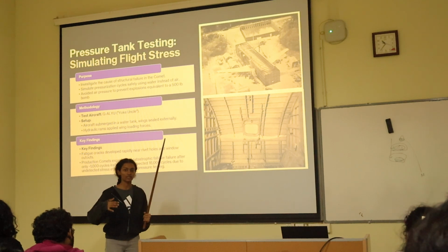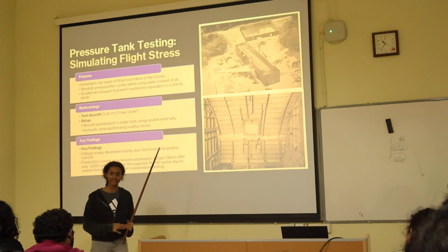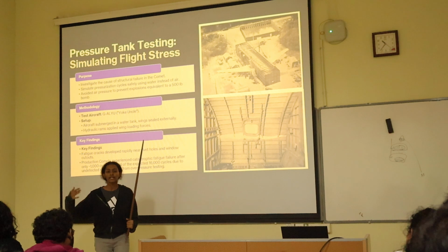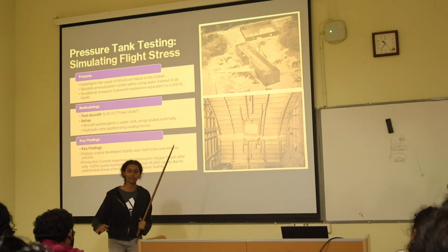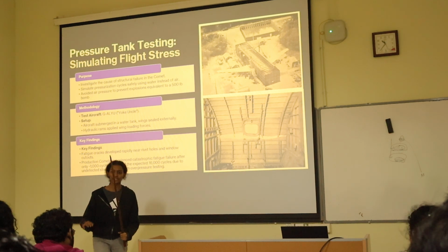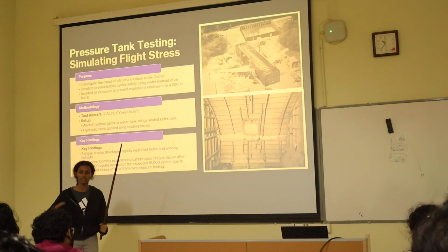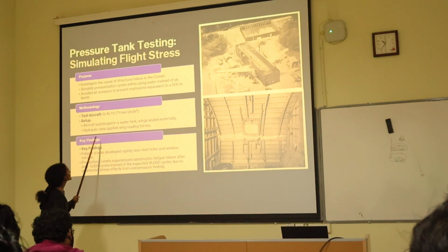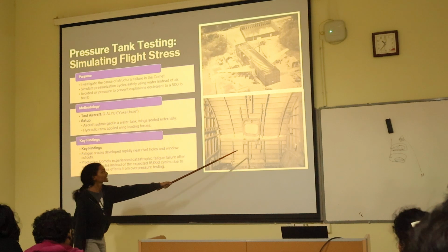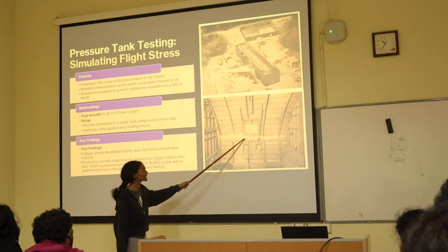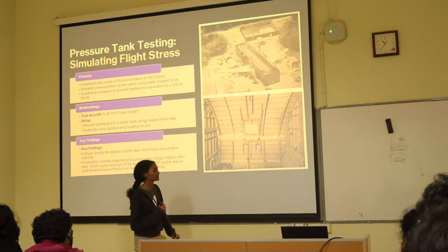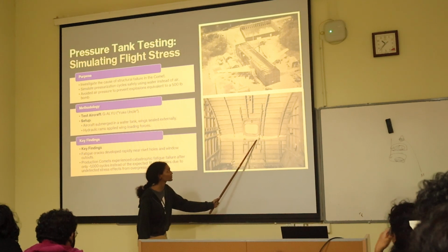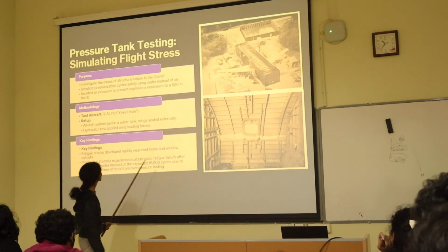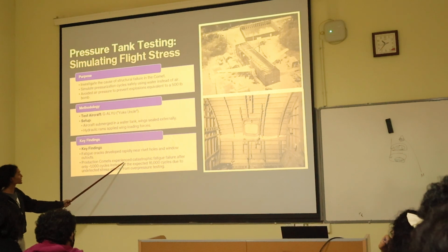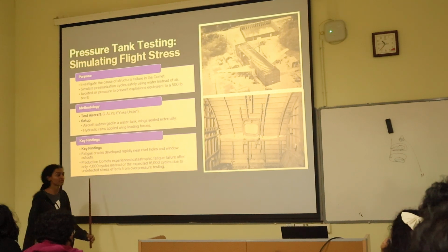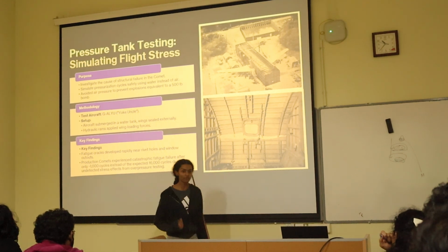So there was water inside the aircraft and outside, and there were hydraulic jacks which kept the pressure cycles and maintained the pressure. And here they noticed that all the fatigue cracks happened at points of high stress concentration. Because of that, from the expected 16,000 cycles, it went down to 2,000 cycles.